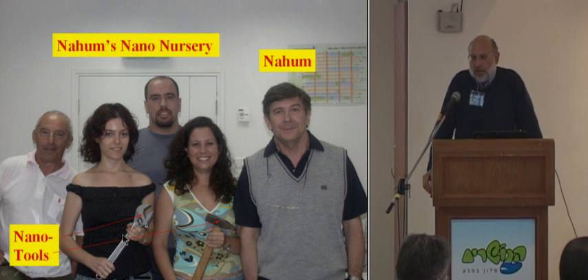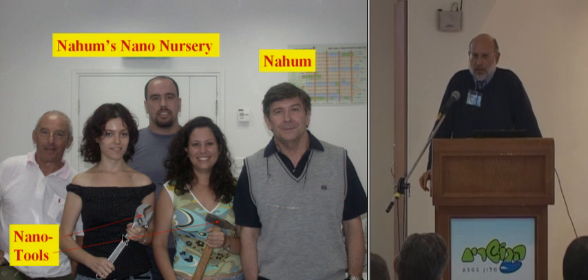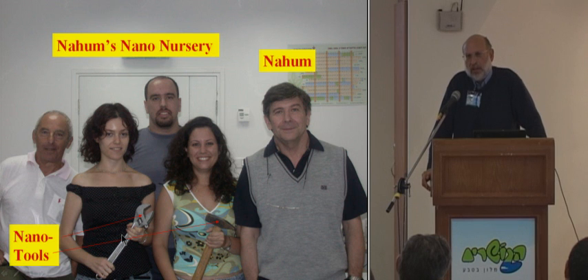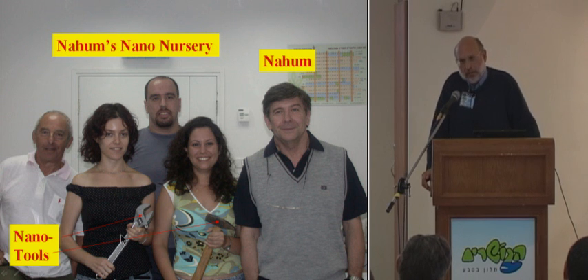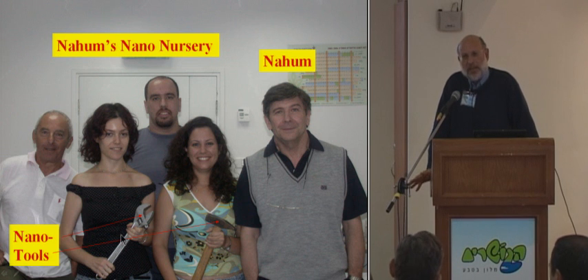But what we do know is that there is an insignificant amount of, say, iron, which is the most ferromagnetic of the magnetic materials, to give us the magnetic moments that we measured. We'd need at least an order of magnitude more iron than the limit of detection in the, I don't remember whether we were using XPS or SIMS. So that's not the explanation as far as we know.